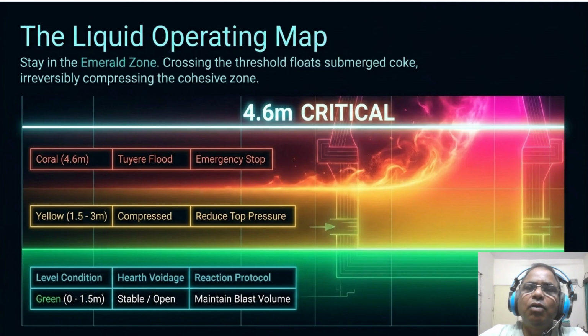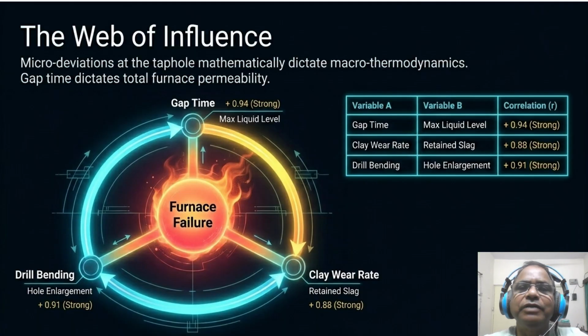This slide shows the web of influence, the mathematical correlation between our key metrics. Notice the R values in the table. Gap time has a 0.94 positive correlation with the maximum liquid level. That's a near perfect, strong link. Clay wear rate is tied at 0.88 to retained slag, and drill bending is at 0.91 for hole enlargement.